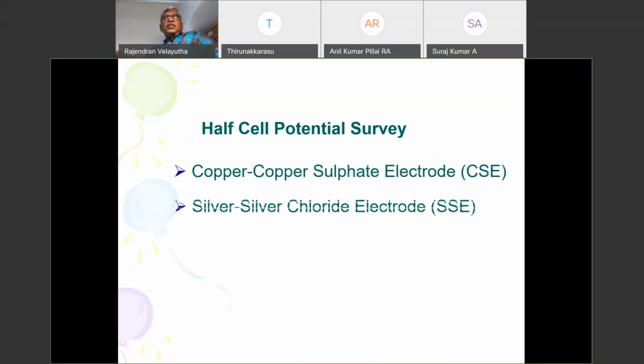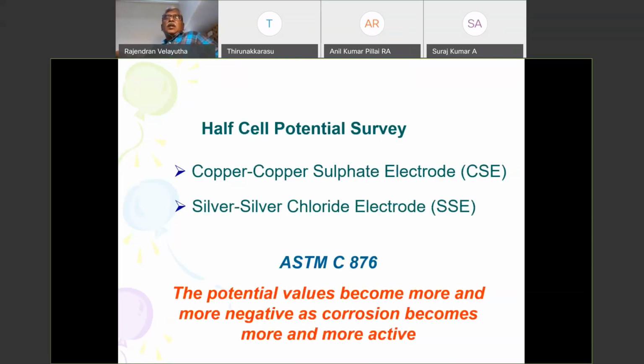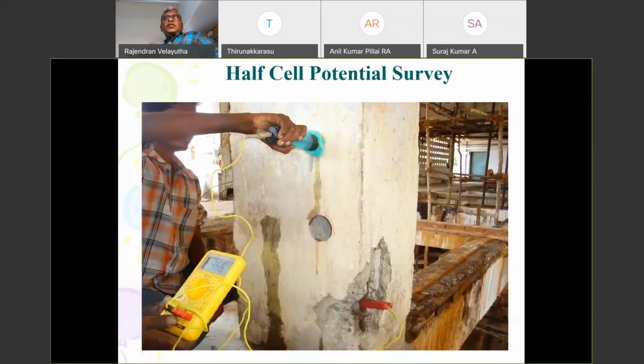The other one is half-cell potential, where we are going to see the rate of corrosion of the reinforcement, where we follow ASTM C876. At FIP, we always go with the copper-copper sulfate electrode. This is a process which is being done. Many of you are familiar with this, where you connect the steel through a multimeter to the concrete cover, and you use copper as your reference electrode. And for making the connectivity, you fill it with a super saturated copper sulfate solution. Thereby, you read the flow of electrons, the current taking place.